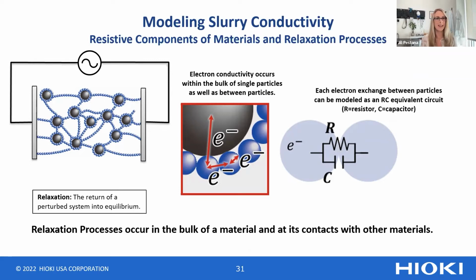It's pretty complex. If you think about it, slurries make up the active material, the conductive particles, and then insulative materials like the binder and the solvent. And so the best way to measure this slurry would be an AC impedance spectroscopy system. There are these relaxation processes that occur within the material and the contact with other material. Understanding the relaxation processes is important to quantify that conductivity. In that middle picture, you can see the electron conductivity occurs not just within the bulk of the single particles, but between particles as the electrons exchange down the chain of conductive additives or particles. Each electron exchange between particles can be modeled as an RC equivalent circuit. So you have there a resistor and capacitor in parallel.